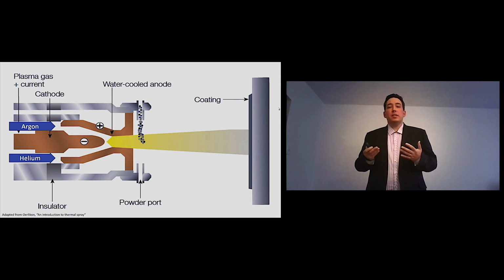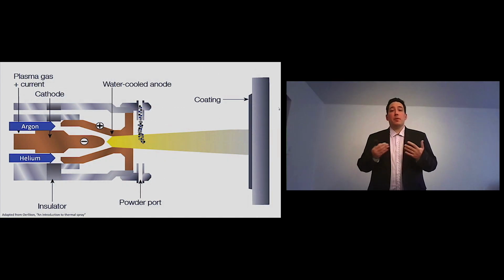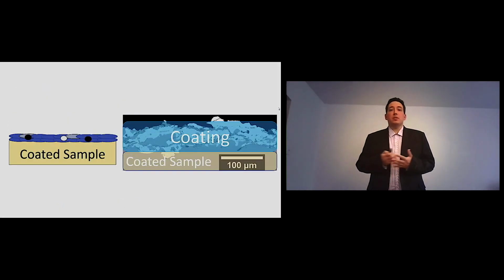Well, we actually did that. By using this technique, we produced a coating using data from literature for the parameters of spray or deposition. This is what we got. So what you see in the top part is the coating, and the bottom, the coated sample. Well, let's remove this box for a moment so we can see the coating.